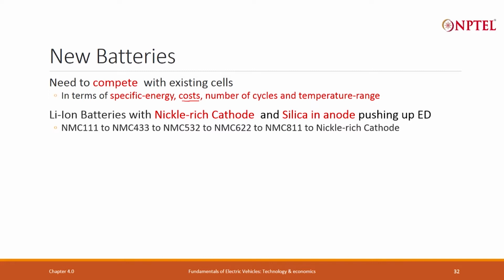Lithium ion batteries that you get today, you will see its cathode will start getting more and more nickel. That is helping increase the energy density, and in the anode you are adding more and more silicon. As I told you, it started with NMC 111, 433, 532, 622, 811 and now nickel rich. So, the nickel rich cathode and silicon rich anode, instead of graphite use more silicon. There are problems in using silicon, it is not as easy to use, but it helps in improving the energy density and reducing cost.